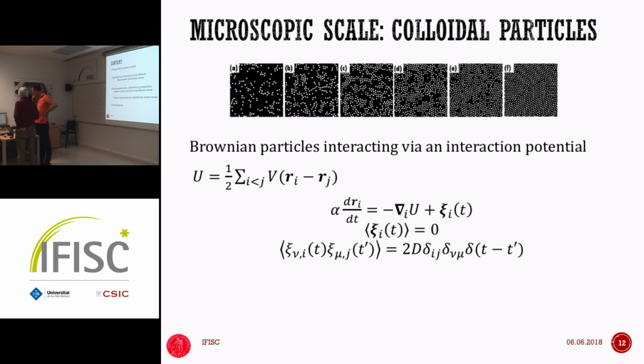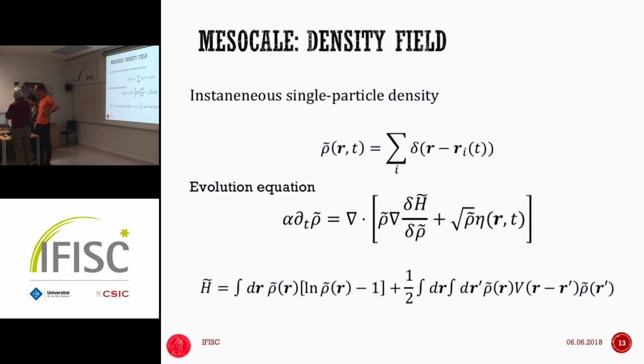Yeah, so you get this, well, you don't get that. I mean, you have lots of delta functions. There's a diffusion term coming from this term, multiplied by noise, and it's pretty tricky. The diffusion term can be written at the free energy level as a log. So it's an entropy, it's an entropic diffusion. And then there is a problem because rho is a collection of deltas, and the logarithm of a collection of deltas, which is mostly zero, is not very clear in the mathematics. No. But you do the maths and you write this formula. Yeah. And then, because at the